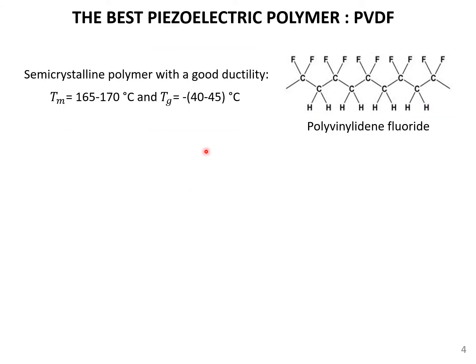If you look at the best piezoelectric polymer, this is the PVDF. It's a semi-crystalline polymer having a very good ductility with a melting temperature close to 170 degrees and a glass transition close to minus 40 degrees.